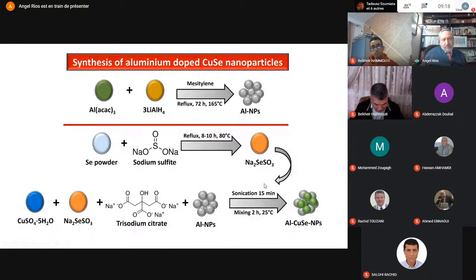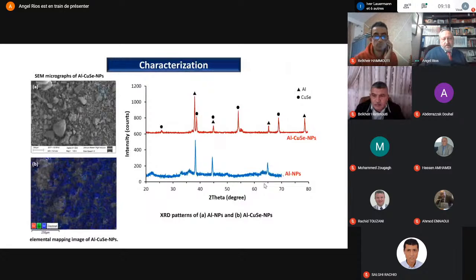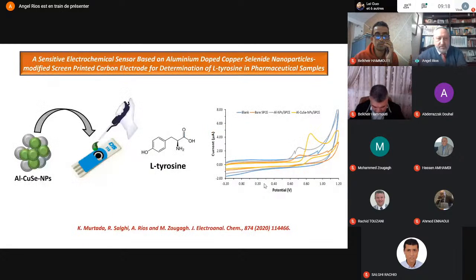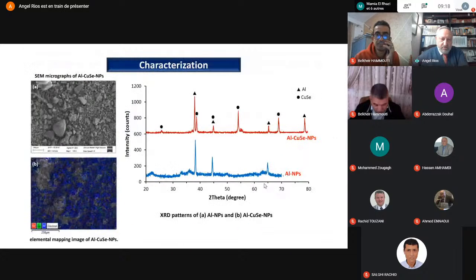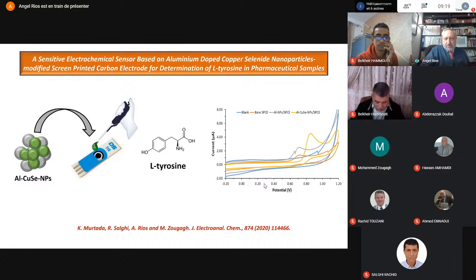Also, another example of the modification of screen printed electrode is the modification with copper selenide nanoparticles on aluminum to determine L-tyrosine in different kinds of pharmaceutical sample. Also, the characterization of the nanoparticle, as you can see in this slide, by scanning electron microscopy, and also by X-ray diffraction in order to check the incorporation of the copper selenide nanoparticle to the aluminum nanoparticle. And also the corresponding electrochemical recording in order to perform the specific determination of L-tyrosine.